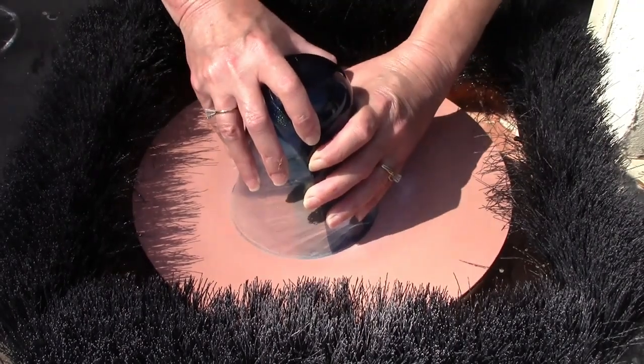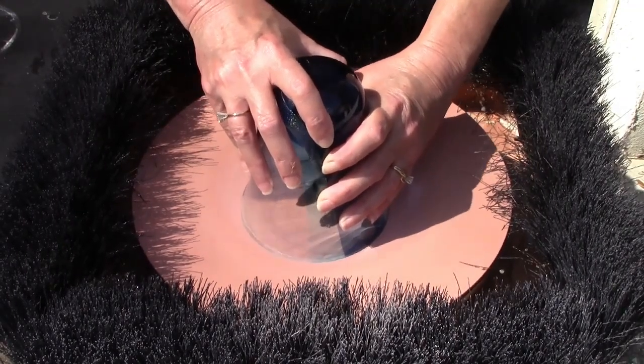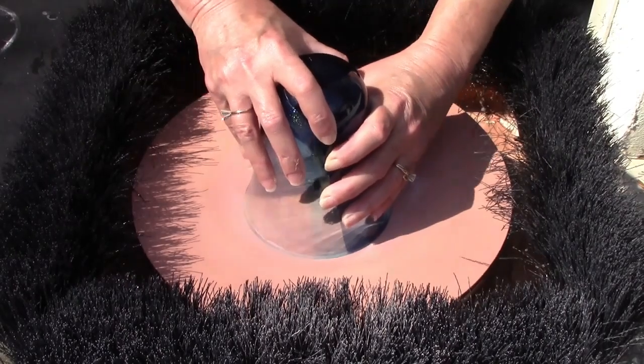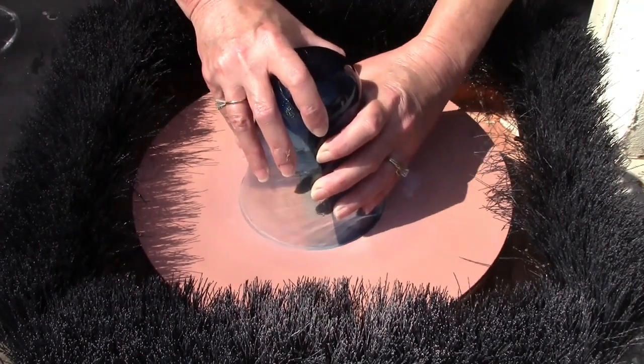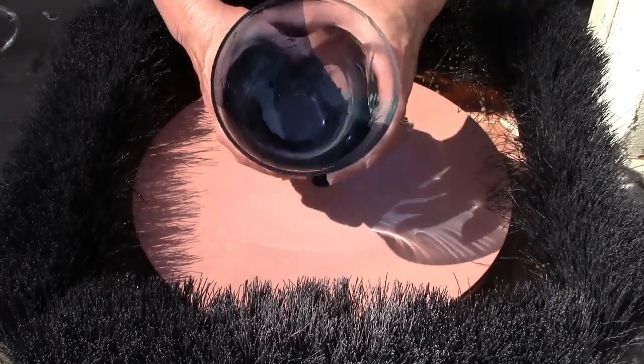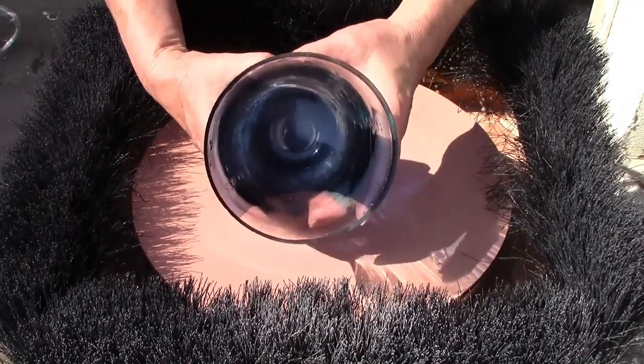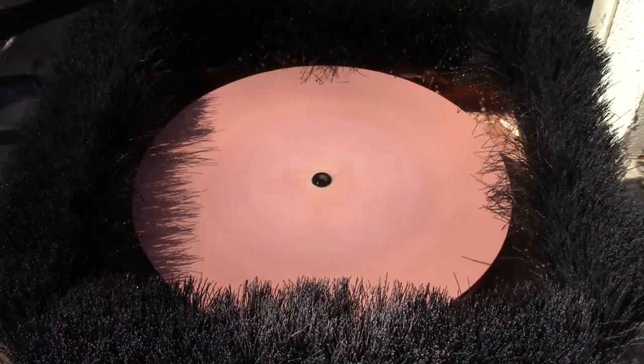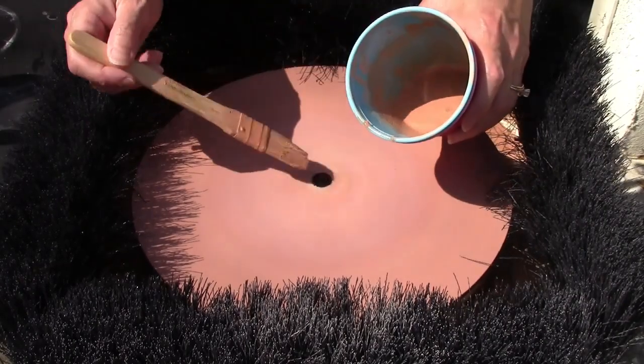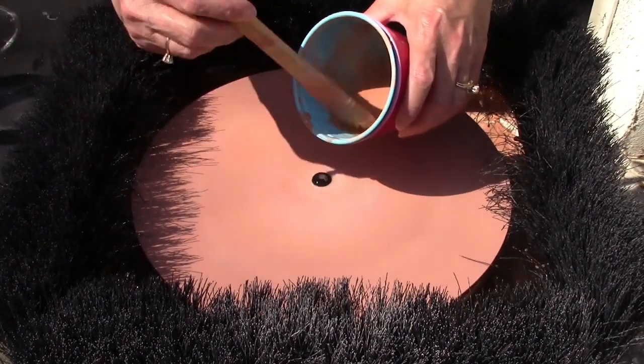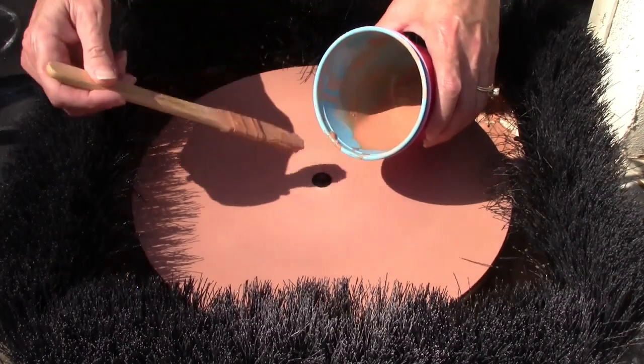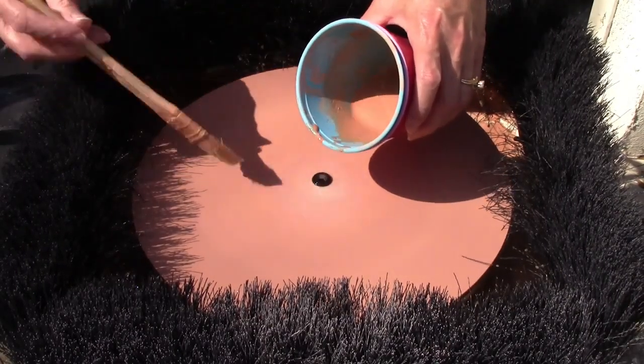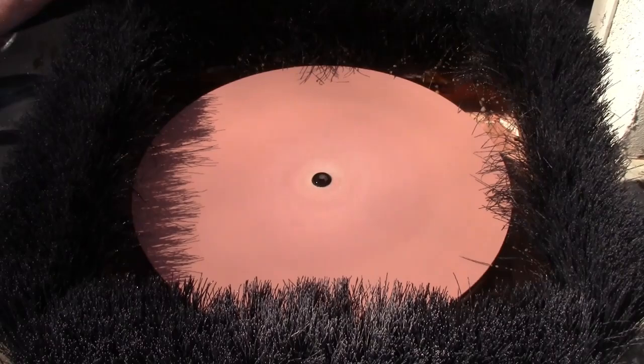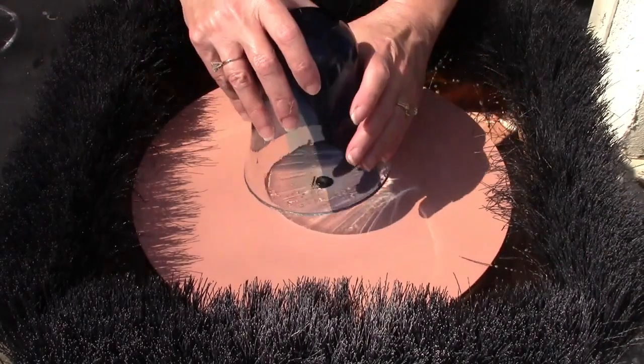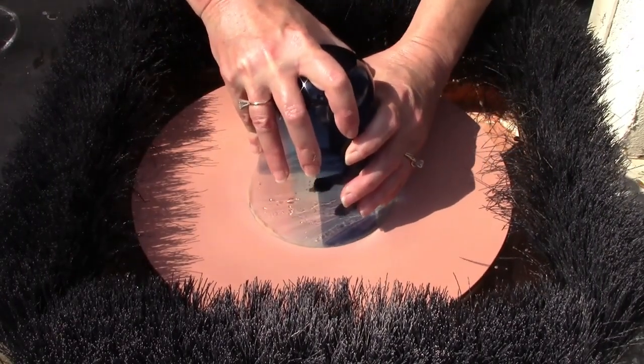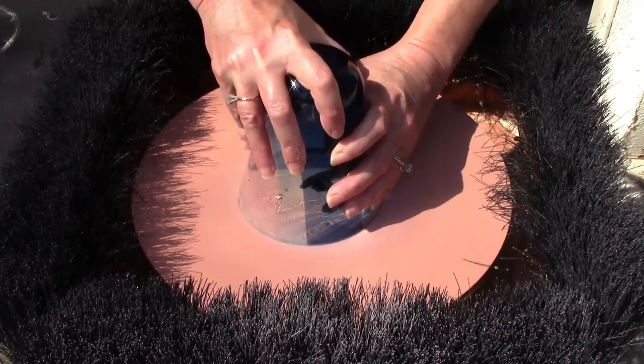When doing this step, I frequently look at the glass to see my progress. It's best if you take the glass off and dry it with a towel, because when it's wet, it looks like the shine is uniform all the way around the rim. But you really have to dry it off to see where there are areas that need a little more attention or a little bit more work. So I'm going to add more of this medium to the felt pad, and this medium kind of washes off as you're going, and it also sticks to the glass. You want to reapply that coating pretty frequently.